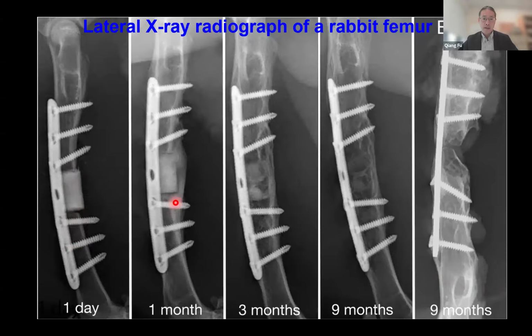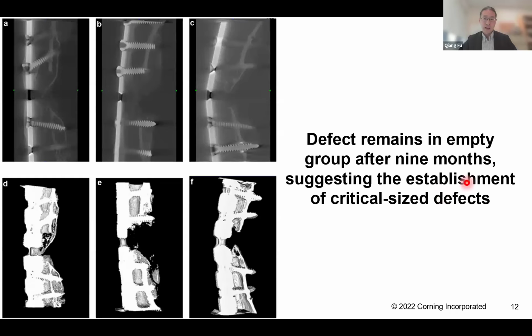After 1 month, we start to see bone grow around the scaffold. At 3 months, the scaffold starts to degrade and bone ingrows into the scaffold. After 9 months, basically the whole scaffold seems to be gone, and you can see bone already integrated very well through the gap. For the empty control, we noticed there's almost no bridging of the gap after 9 months. We looked at additional samples and found that after 9 months, almost all these empty defects still remain, which means we have established a critical size bone defect model for our study.